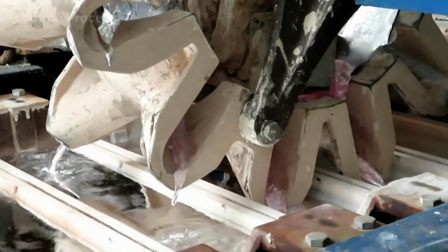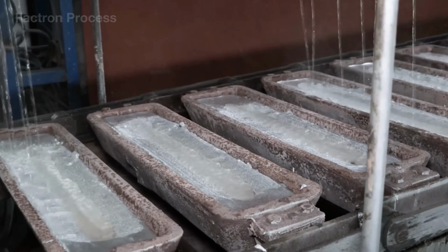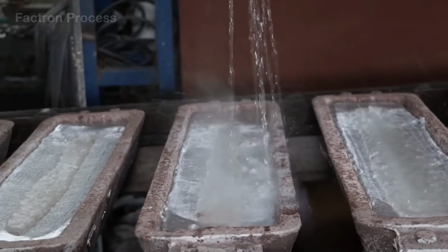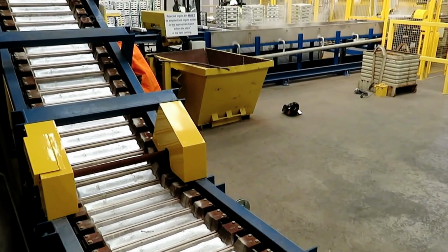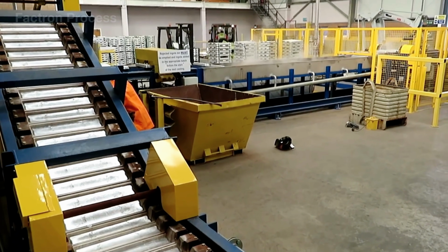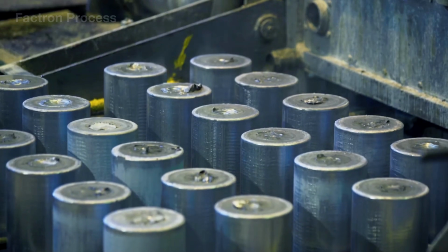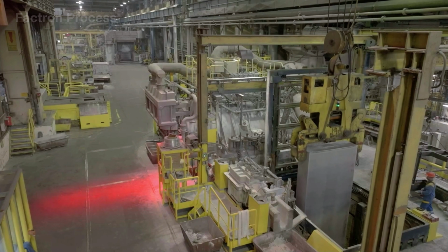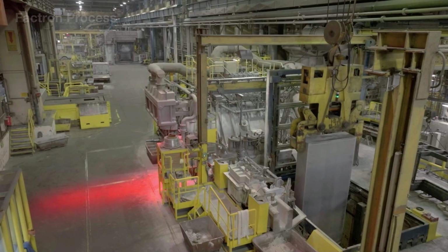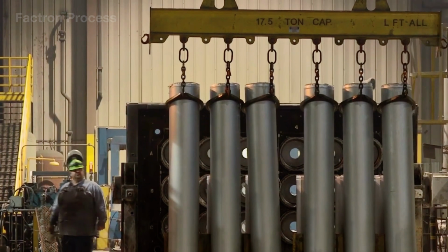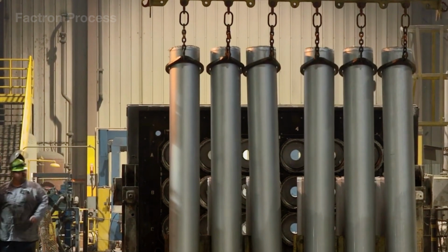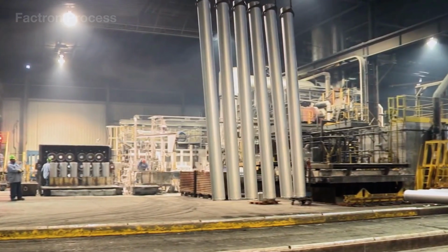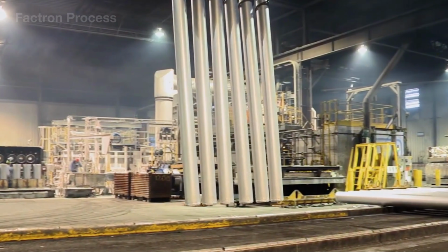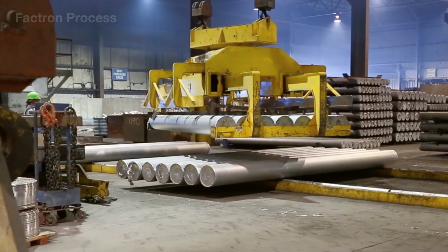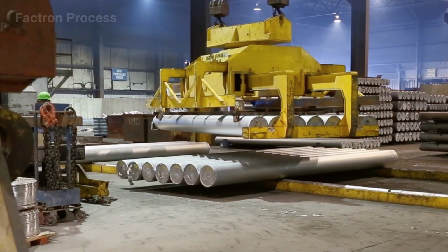Both the pouring rate and cooling speed must be carefully controlled. If the metal solidifies unevenly, internal porosity, cracks, or inconsistent alloy distribution may develop inside the ingot. Once fully solidified, the ingots are removed from the molds, trimmed to eliminate defective ends, and inspected for surface flaws. Depending on their intended use, they may be formed into ingots, cylindrical billets, or large slabs for further rolling, extrusion, or machining into new products.